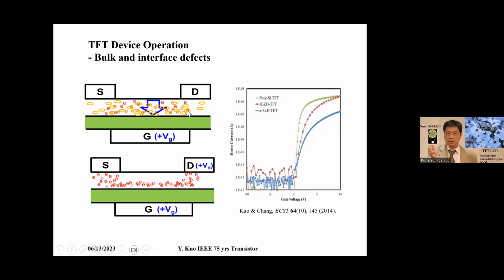For oxide, the traps are oxygen vacancies. So during operation, when the gate voltage is applied, first the traps have to be filled. After the traps are filled, then a conducting path is formed. Then the transistor turns on. So this shows the three major production technology TFT transfer characteristics.